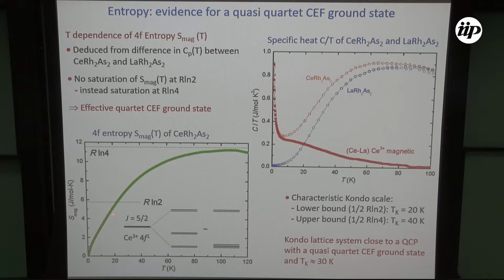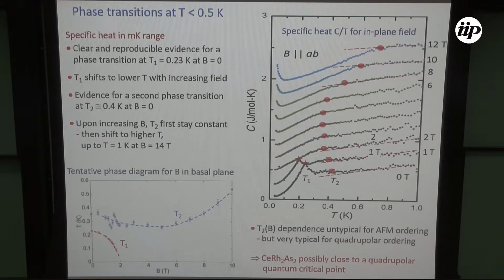And further on, you can now extract from the entropy, this is a standard method, what the Kondo scale is, and depending on whether you assume a doublet or a quartet, you get either 20 Kelvin or 40 Kelvin for the Kondo scale. So we can say we have a Kondo scale of the order of 30 Kelvin. Then we went to lower temperature, specific heat in the millikelvin range. Here shown as C versus T as a function of magnetic field, between 0 Tesla and 12 Tesla.